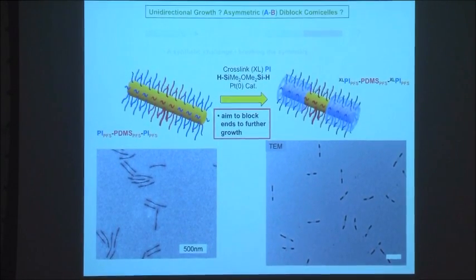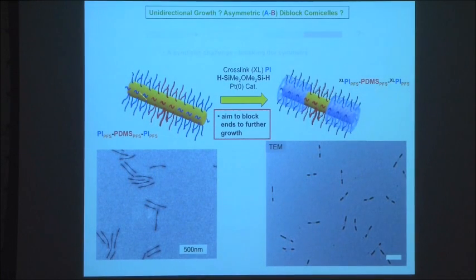The way we do this is we start off with tri-block co-micelles. We start off with a PDMS seed micelle with the red corona here, and then we grow on the ends PFS-PI, so we have a polyisoprene corona in blue on the ends. And what we then do is cross-link the polyisoprene using this platinum-catalyzed hydrosilylation. So this cross-links the ends. It doesn't cross-link the PDMS because it's got no vinyl groups. And the aim here is actually to block the ends of the cylinder through this cross-linking process.